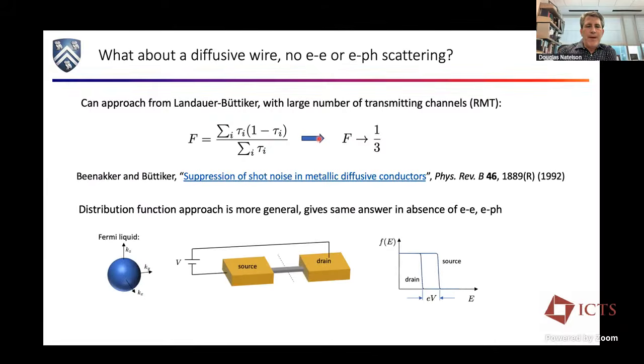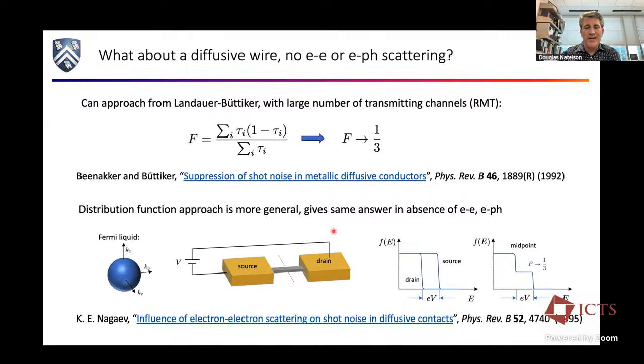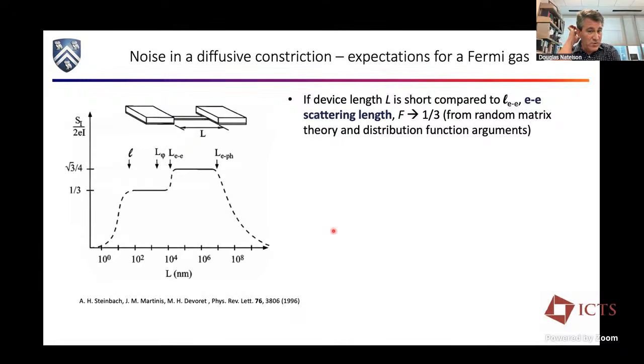A better, more general way to think about it in some sense is to ask what the distribution function of the electrons looks like in the middle of the wire. What you find is that in the absence of electron-electron energy exchange and electron-phonon energy loss, the distribution function in the middle of the wire is some funny two-stepped thing. If you take the Boltzmann equation and ask what the current correlations are for this funny two-stepped non-thermal distribution function, you again get that the Fano factor is supposed to be a third. This is kind of a theme with some of the stuff I'm pushing these days: this is something that has been looked at for a long time in the world of mesoscopics in ordinary weakly correlated metals.